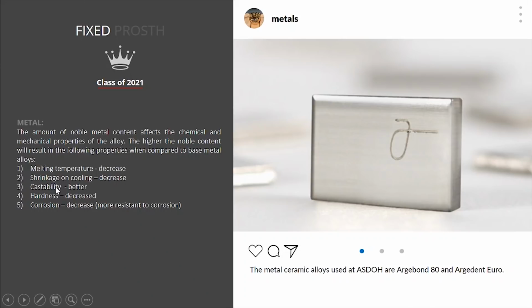Castability is just the ability for the metal to fill in that wax pattern, the void in that investment material. So we're going to say that the high noble metal has better castability. In terms of hardness, just think of gold. Gold is a softer metal, so you're going to say that noble metals have decreased hardness compared to a base metal. And when it comes to corrosion, we know that noble metals are pretty stable, so those are going to be less corrosive when you compare them to base metal.